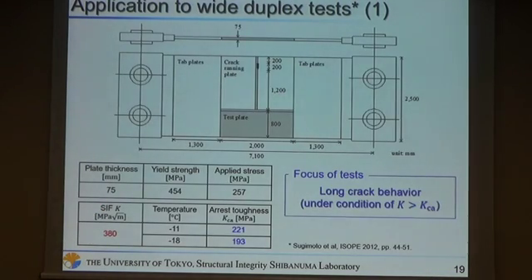The second validation is application to the wide duplex test. This figure shows the configuration of the specimen, and this table shows the specification of the test plate and test condition. The focus of the test is long crack behavior under the condition where the stress intensity factor is larger than the arrest toughness KCA.